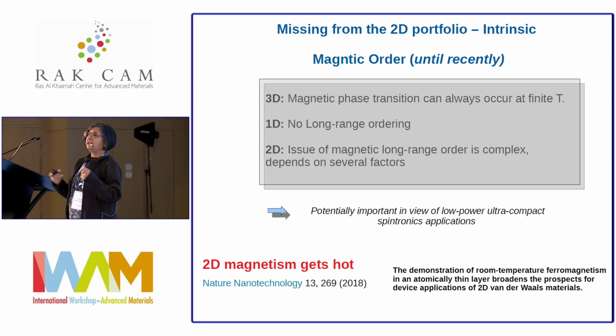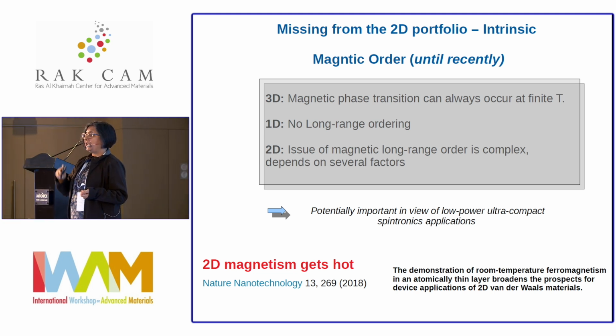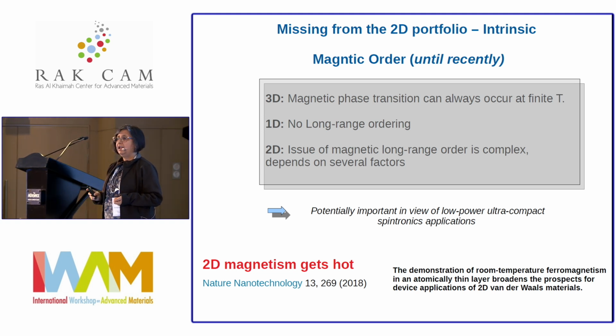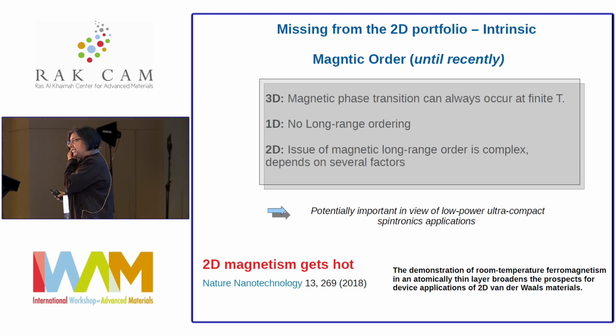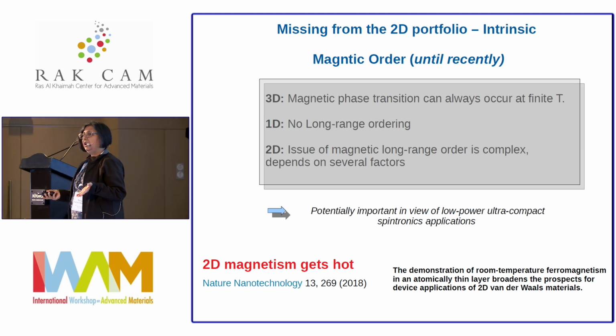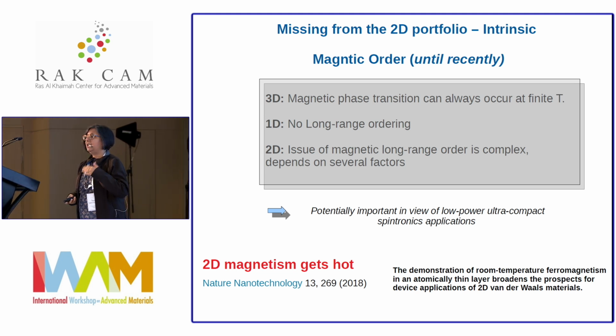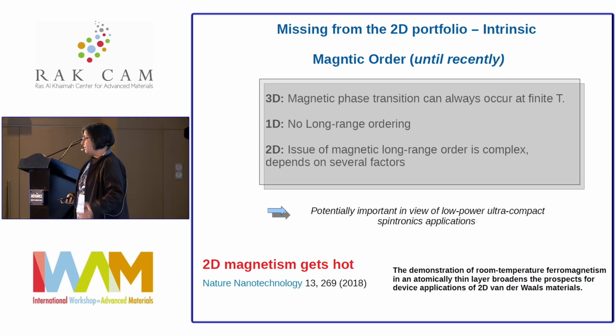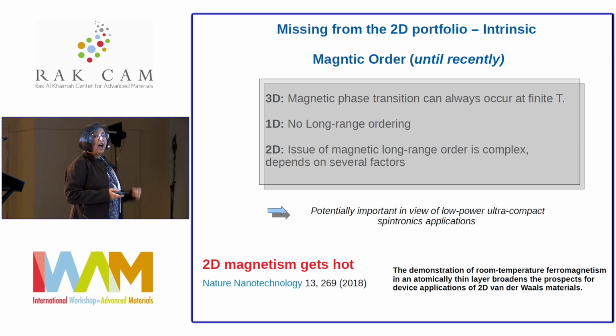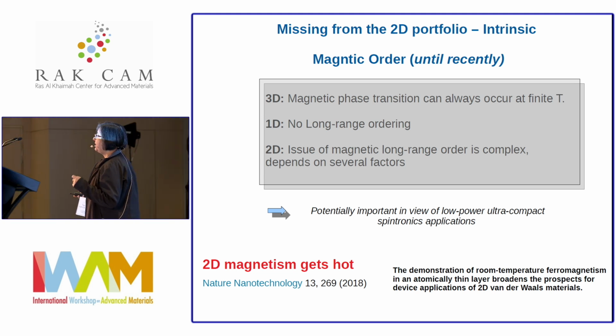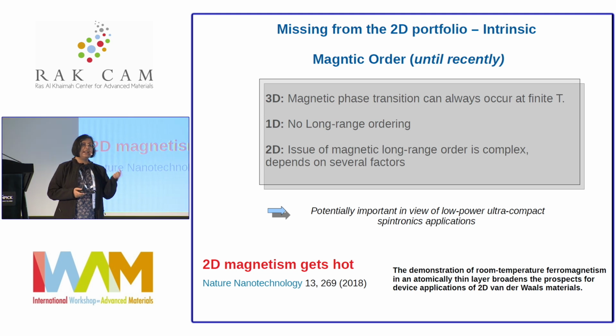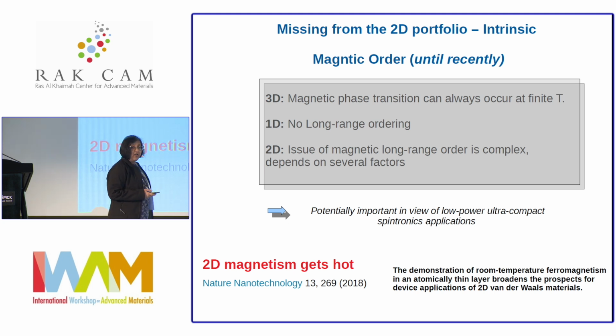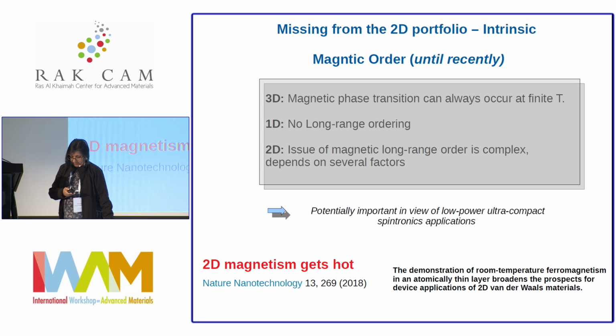If you have a Heisenberg model with a perfect rotational symmetry of the spin, then the Mermin-Wagner theorem says actually there is no phase transition, or the critical temperature is 0 Kelvin, because any amount of thermal fluctuation destroys that magnetic order. However, if you can introduce some amount of magnetic anisotropy, the Ising model is the other extreme limit where you are at the completely anisotropic limit, then the magnetic ordering is possible in 2 dimensions.